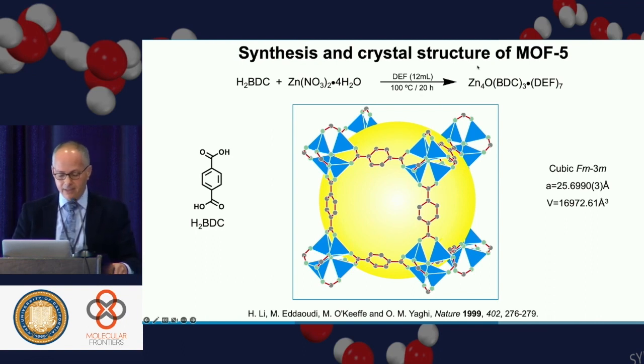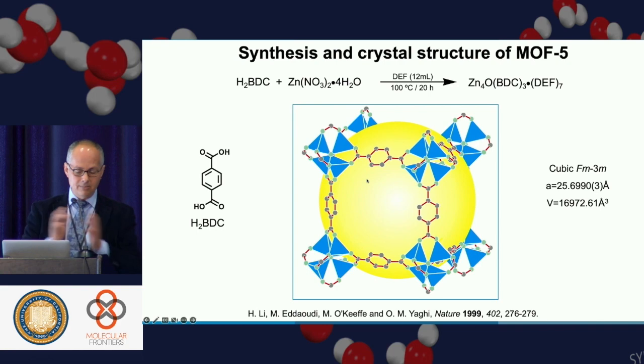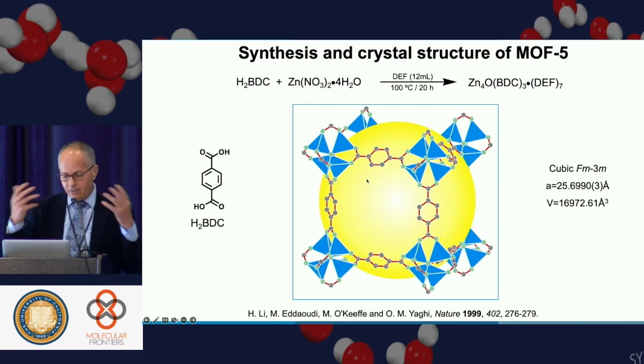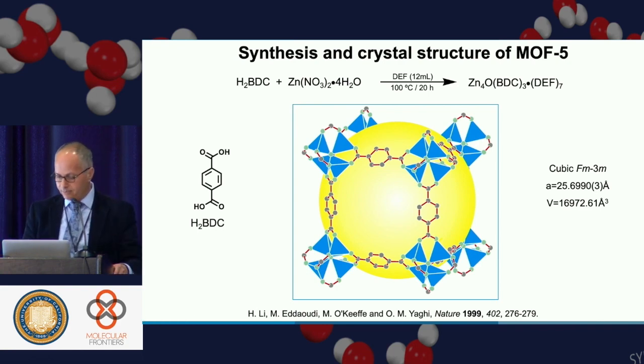Then we made this one. This is MOF-5. This is a metal, zinc oxide units. Inorganic chemists call this core the basic zinc acetate structure, which has been known since Bragg solved the first crystal structures of these basic zinc acetate structures. And you see here it has an openness, that the yellow ball indicates a space within which things can be incorporated, like for hydrogen storage or carbon capture.